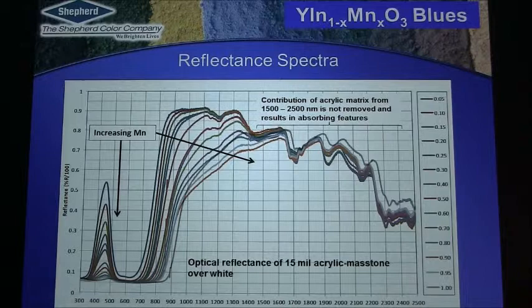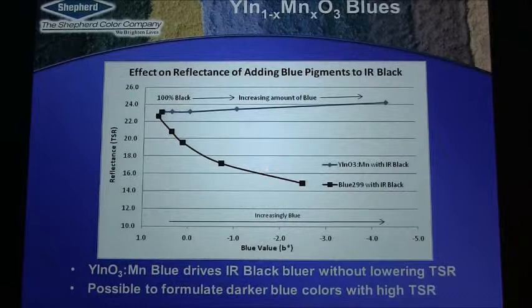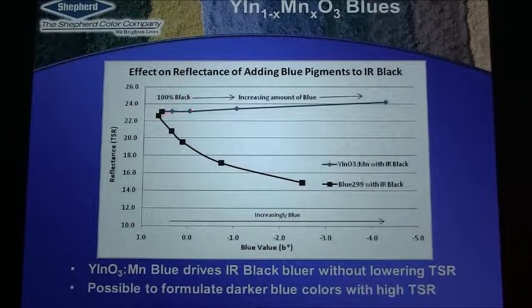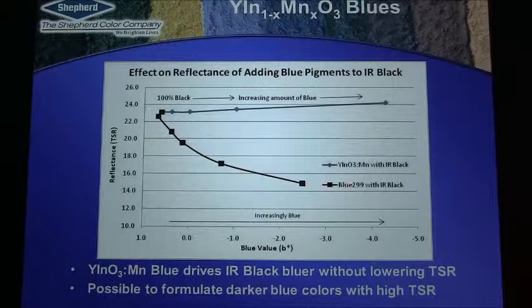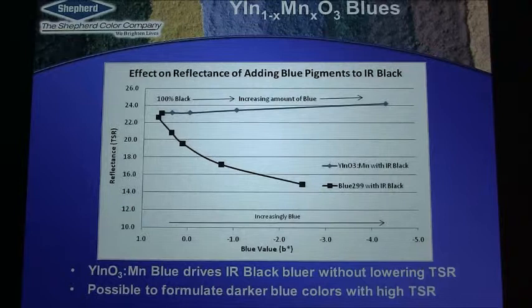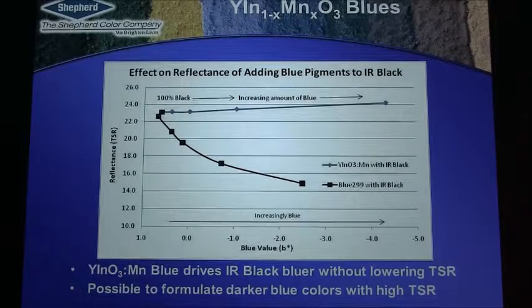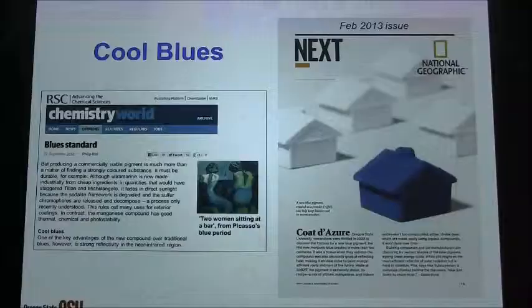In fact, the Shepard Color Company has done a lot of work now. They mixed our blue with the IR black, and they can see the IR black does not have a very high reflectance of near infrared solar radiation. But as you can see, when they add our blue to this black, it actually increases the reflection, whereas when they add the cobalt blue, it decreases the reflection. So definitely, as they said, you can formulate darker blue colors with a very high solar reflectance using our pigments.